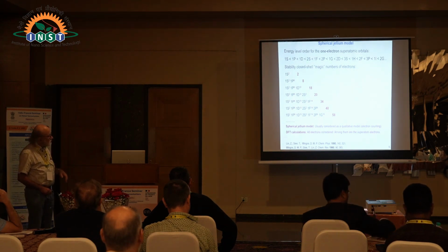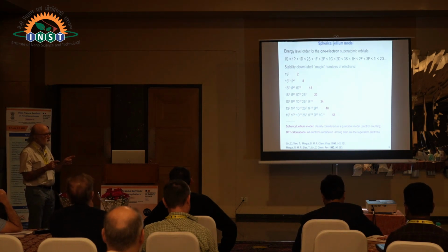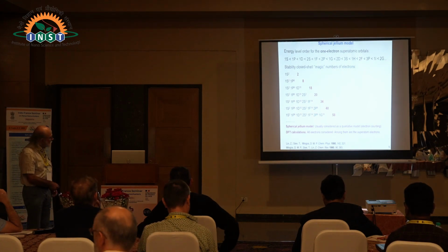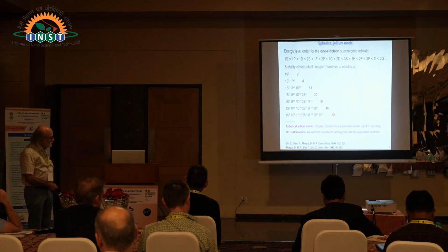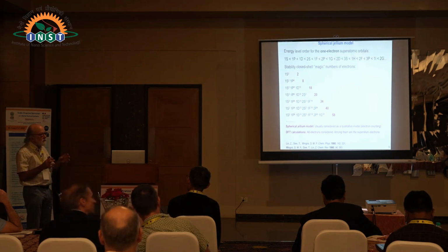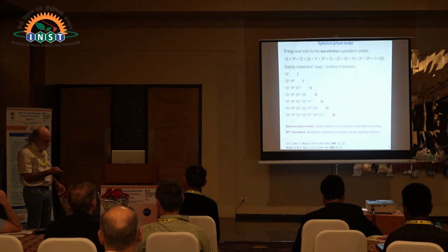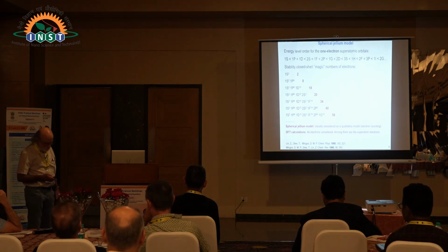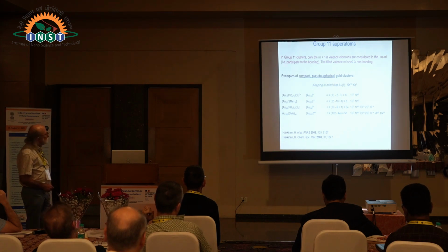In DFT calculations, these electrons are the electrons which are associated with metal-metal bonding within the sphere. When you consider a molecule, you have ligands and so on. DFT calculates all the orbitals, all the electrons, and we have to identify among the molecular orbitals, the Kohn-Sham orbitals, those which can be considered as the superatomic orbitals. So just a few examples.